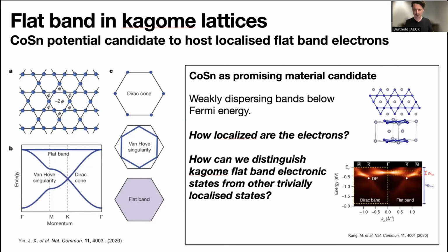Now, the question is, where can we find that? And that's actually the challenge. Unlike, say, moiré materials, where by virtue of just combining two atomically thin material layers, we have a very controlled environment, it turns out it's quite hard to find Kagome materials that have a very well-defined electronic band structure of the type shown here on the left.